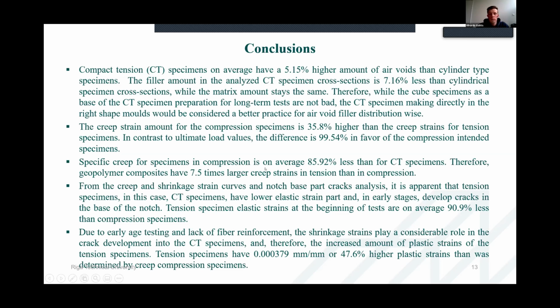And from the creep and shrinkage curves and the notch base crack analysis, it is really apparent that tension specimens, in this case compact tension specimens, have a lower elastic strain path, and in early stages they develop unwanted microcracks in the notch base, and therefore tension elastic strains at the beginning of the tests are on average 90% less than in compression specimens.